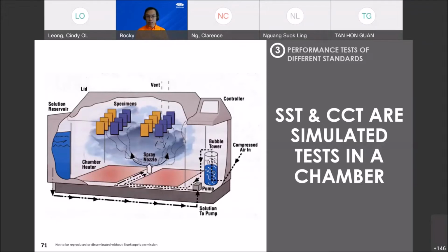So SST, salt spray test, and CCT, cyclic corrosion test, are essentially simulated environment tests, right? So they put the sample, as you can see these blue and orange samples, in the chamber, and then there's actually a spray nozzle, where a certain type of solution is sprayed out, to simulate a more corrosive environment. And the way they classify whether the product can last for C2, C3, C4, and so on, is based on the duration of the tests, which I have shown earlier, and which I will also revisit later.